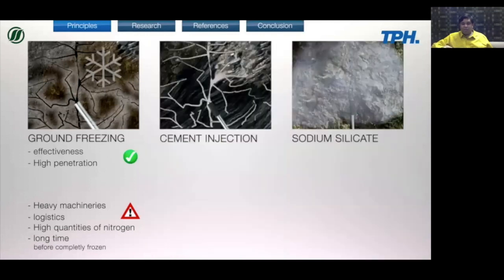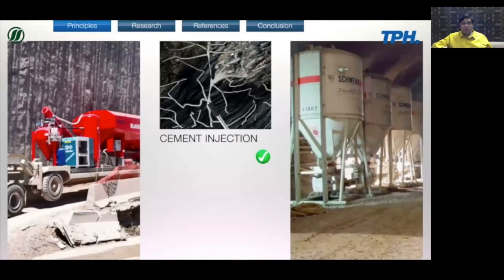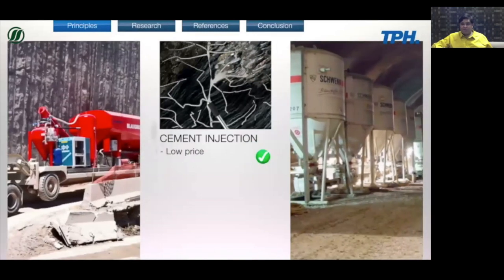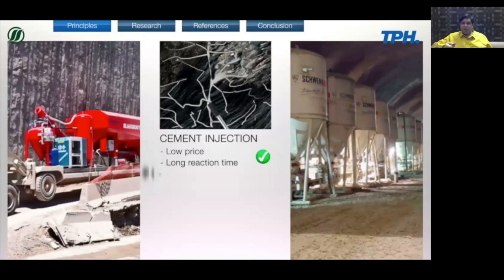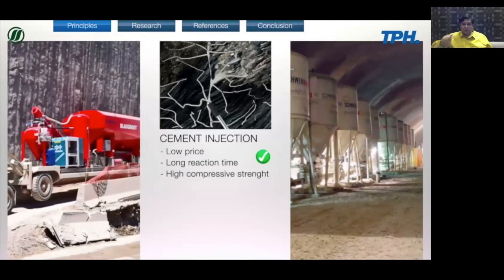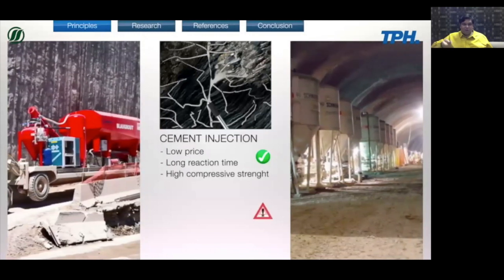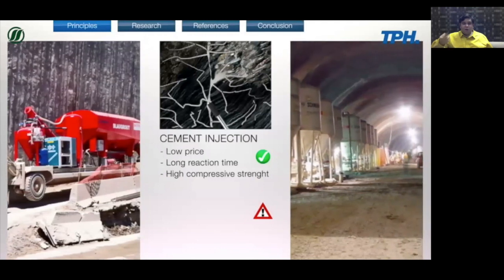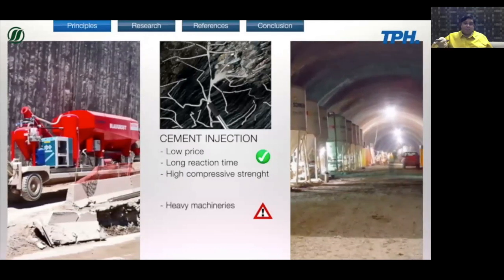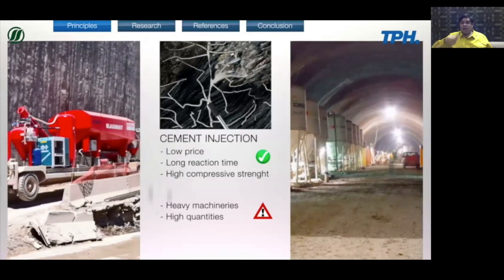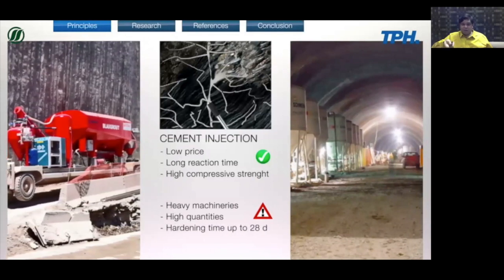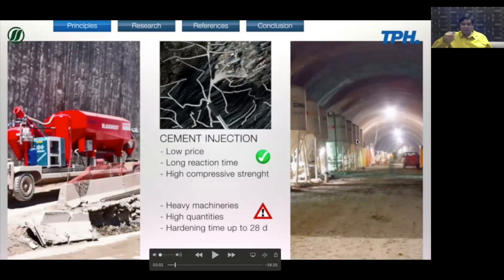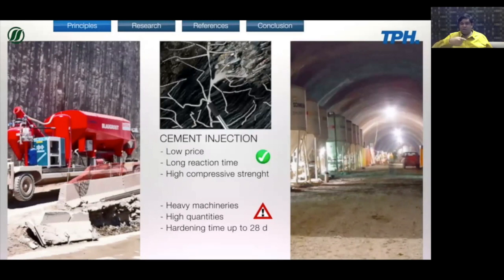Some of the other historic types of injections used, the most common one I would say, even in India, is cement injection. So we have either cement-based materials or microfine cements. These are low in price. They have a long reaction time, but the upside is that they also have a high compressive strength. With a good admixture and everything, you can get strengths up to about 50, 60, 70 newtons out of these kinds of materials.